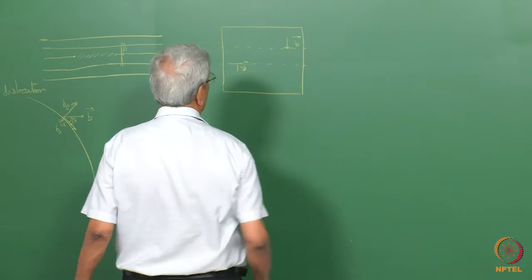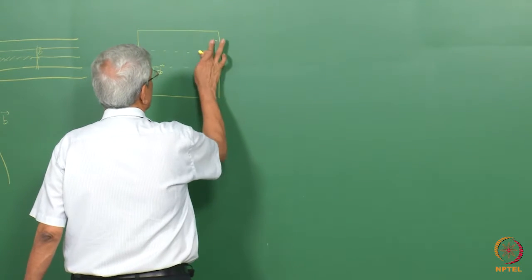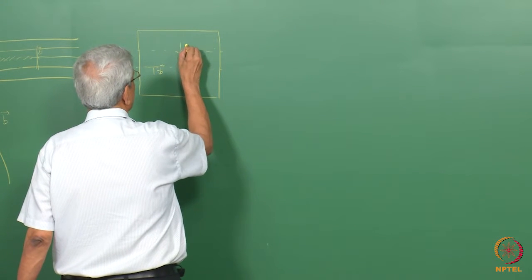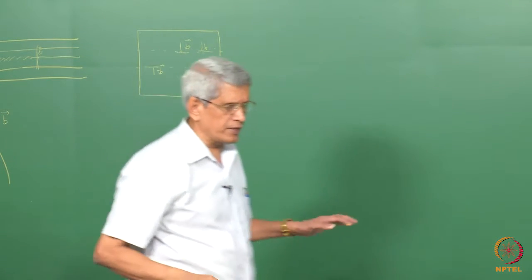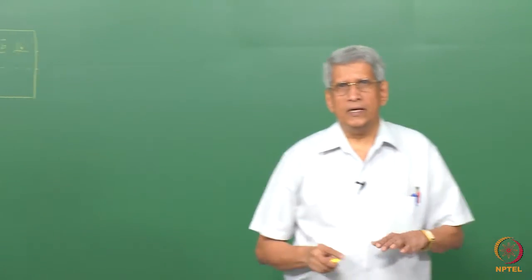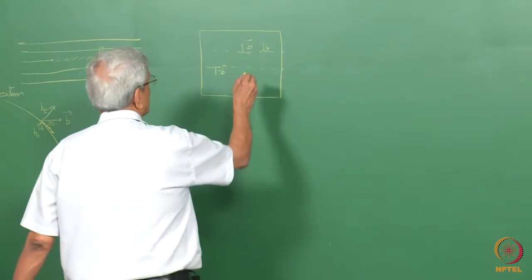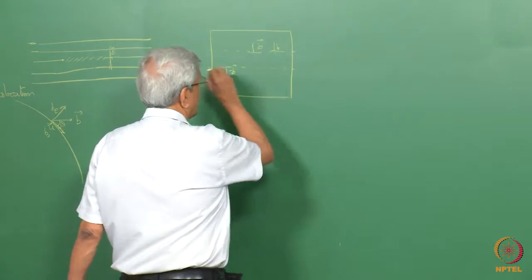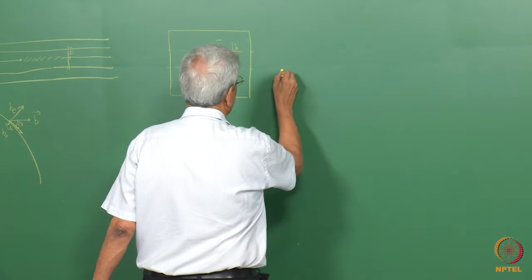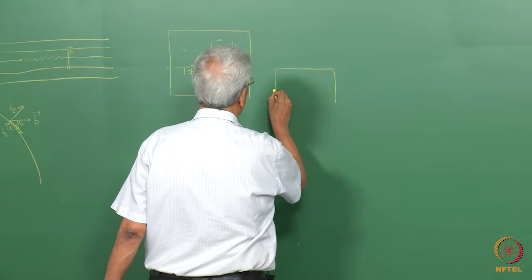When the dislocations are within the sample and are moved partly, suppose this dislocation is lying here, and from here it has moved a distance and reached here. Actually the dislocation has done some work, it has shifted some plane, but shape deformation has not taken place. When does the shape deformation take place? When the dislocation completely comes out of the sample surface. Like the way we have considered it, in this case the dislocation will come out.